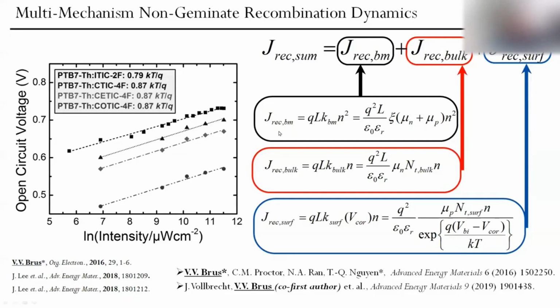So previously, quantitative analytical models were derived and developed for bimolecular recombination losses in organic solar cells and for trap-assisted recombination in the bulk. My particular contribution was to propose a model which describes trap-assisted recombination at the surface, at the interface between the active layer and electrode, and then we have a complete picture of all the different components of non-geminate recombination which cause